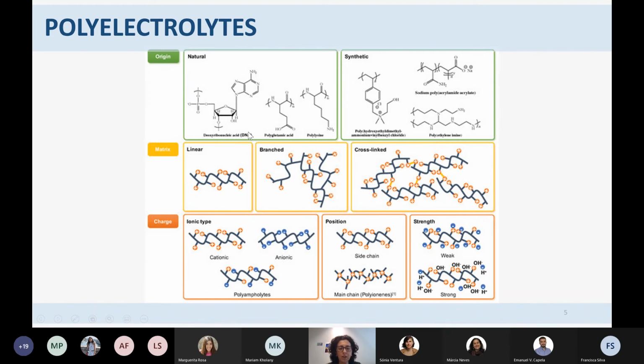In the natural, we all have DNA, as you all know. And in the synthetic, we have PVA, for example, displayed here. In terms of the matrix, they can be linear, branched, or cross-linked. When they are cross-linked, we have ionic interactions between the branches that are so strong that they keep the polymer in a specific shape. In terms of charge, they can be cationic if the backbone of the polymer is cationic, anionic if the backbone of the polymer is anionic, or polyampholytes if they have both positive and negative charges in the backbone. Then it depends on whether the charges are on the side chains or on the main chain. And this gives our polymer specific mechanical properties that we'll discuss in a bit.